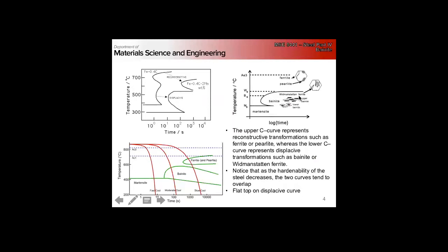martensite. And here, you can look at our continuous cooling curve. With very fast cooling rates, we miss the nose of Bainite and we come down directly into the martensite. If we have intermediate cooling, we come across Bainite. With slow cooling, we cross into the nose of the ferrite and pearlite region. And you can see here, depending on how wide this is, we may completely go to pearlite, or we may cross into and get some Bainite as well.